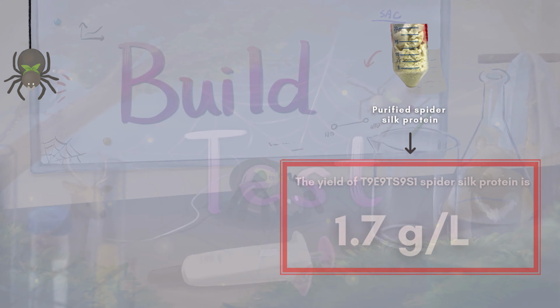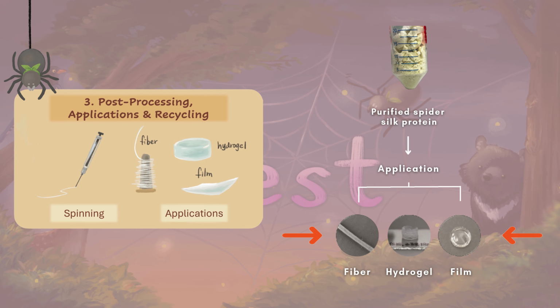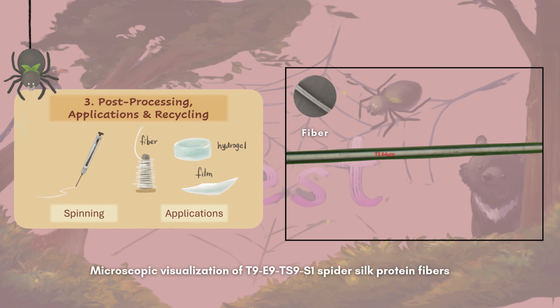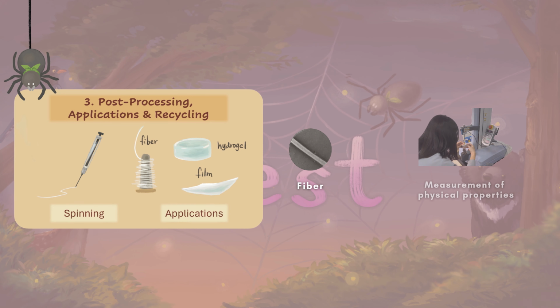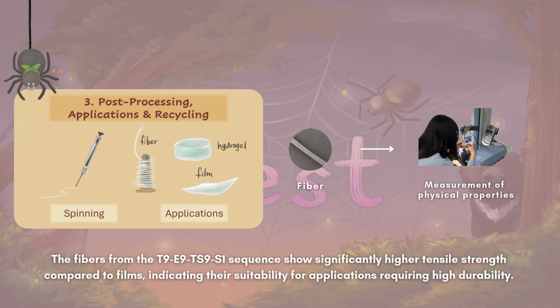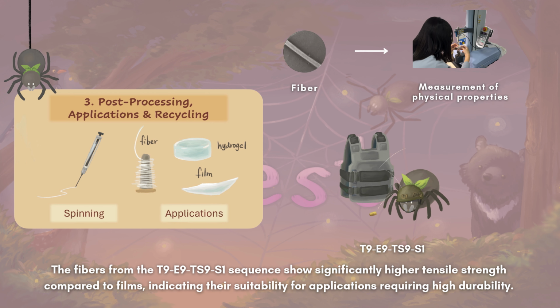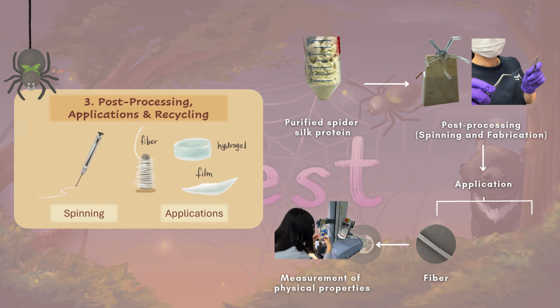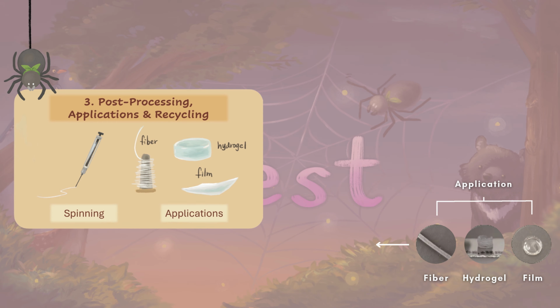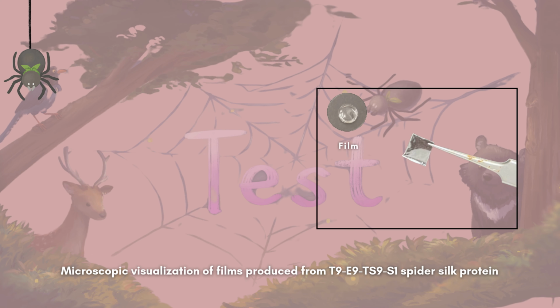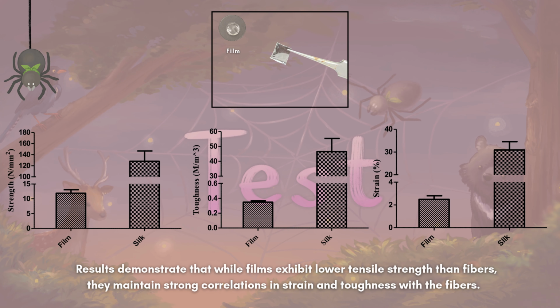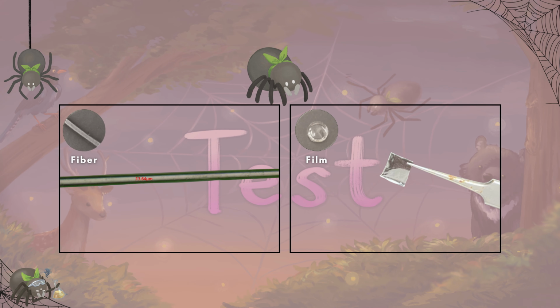large-scale production. For testing, we focused on two main post-processing techniques. First, fiber spinning. We used the fibers produced from the T9E9TS9S1 sequence for fabrication. Tensile strength testing showed that these fibers exhibited high tensile strength and flexibility, making them ideal for high-performance applications like textiles or military uses. Second, film casting. The spider silk HFIP solution was cast into Teflon molds to create films. In tensile strength tests, the films displayed lower tensile strength than the fibers but maintained strong correlations in strain and toughness, preserving the core mechanical properties of the protein.